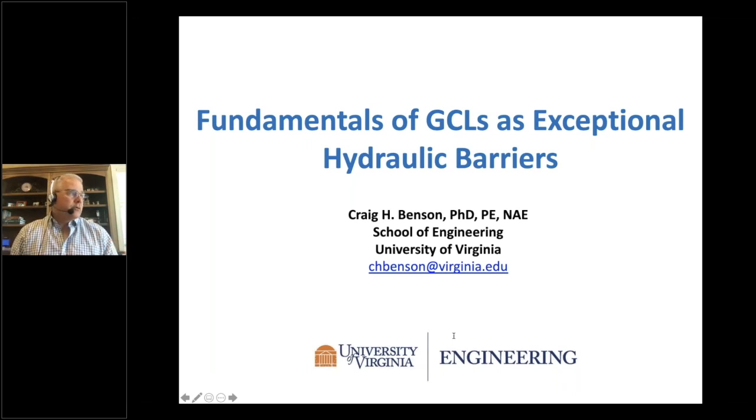Due to a couple of factors, the tortuosity coefficient is smaller. Essentially, because the pore space is so irregular and small, the pathways through which molecules need to move are more tortuous and the diffusion coefficient is lower. But another equally important issue is essentially an osmotic hindrance.